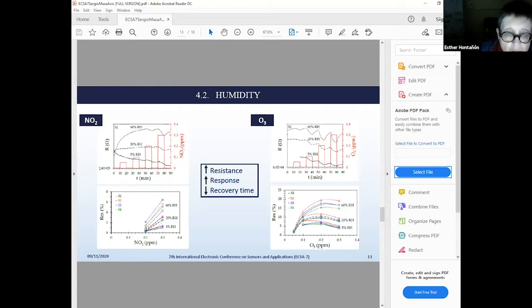With the humidity, all the sensors saw an increase of the response, but none of them was able to detect levels of nitrogen dioxide below 200 ppb. In the case of ozone, the situation is the same, and the responses are higher too. In this case, we were able to detect even 50 ppb with a response of 1%. The reason why this is not increasing continuously with increasing concentration is, we suppose, because even if the recovery time reduces with the level of humidity in the air, the recovery was not full even at the highest humidity. So after the cycles, there should be some accumulation or saturation of gas in the sensing layer, which makes the response not increase continuously with concentration, but reach a kind of plateau.